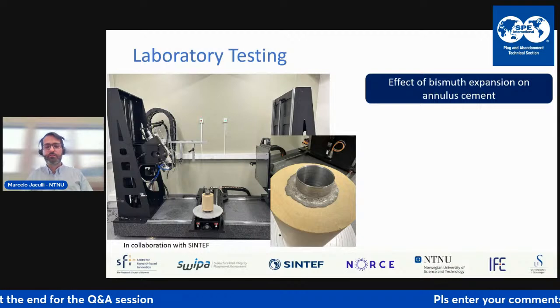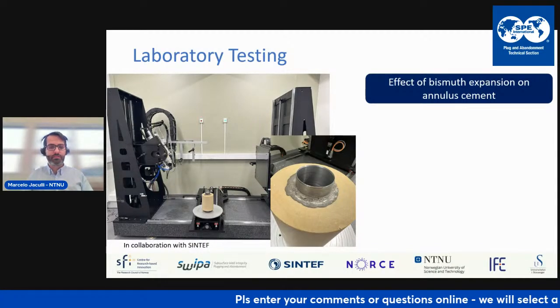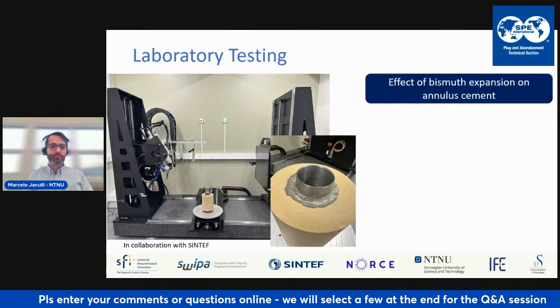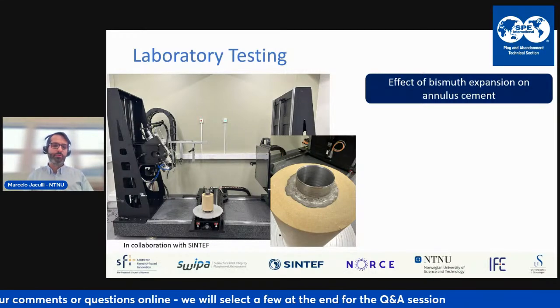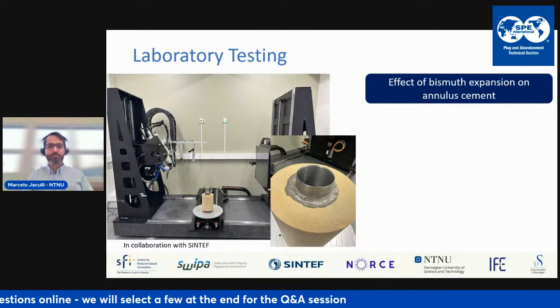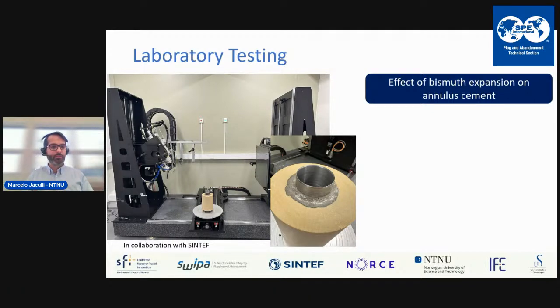Another thing that we did was testing the effect of the bismuth expansion on the annulus cement. This was done in collaboration with SINTEF with a CT scan. So we have here a pipe and the cement behind it, and then we set a plug inside the pipe. Due to the plug expansion, you expect the pipe to deform as well.